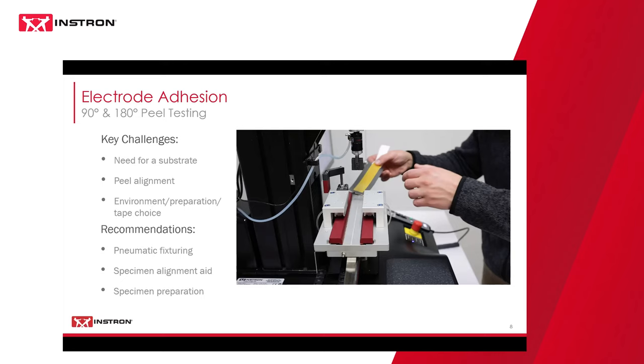However, when you need to add that substrate, it not only adds to the preparation time between each test, but it also adds to the cleanup time between each test. And if you've ever had to do this with a substrate, you know that peeling off an anode or cathode can be pretty messy and undesirable at times. 90-degree peel testing, on the other hand, is usually optimal for throughput because it doesn't need a substrate to maintain the proper angle if done correctly. Some cathodes do still require a substrate with 90-degree peel testing. Sometimes they almost crack too easily, so you do need that rigid body to attach them to. But for the majority of testing, and especially for anodes, you can usually get away without a substrate by clamping it properly and having the right size specimen. So that is a benefit of the 90-degree peel test.